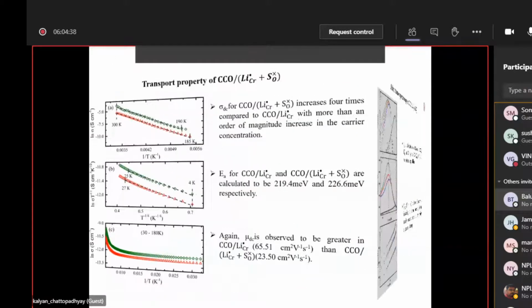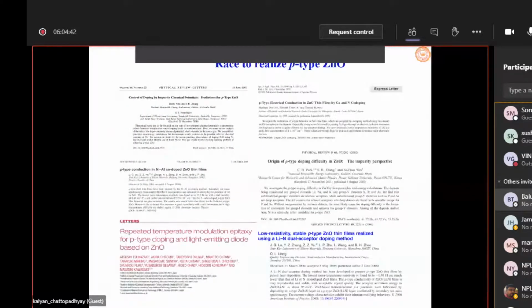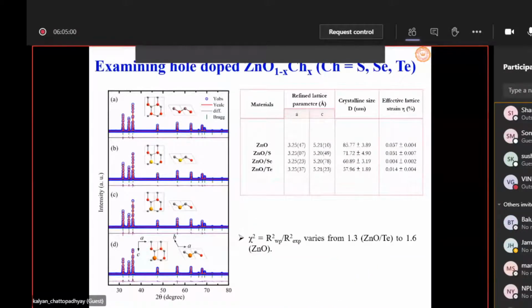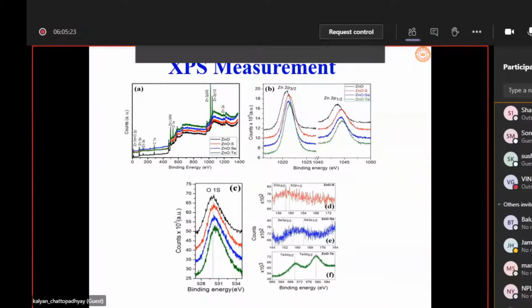I will just take 1 or 2 minutes more to touch upon another very interesting system, that is the P-type zinc oxide. There are lots of papers and work going on about how to achieve this P-type zinc oxide and whether they are stable or not, etc. I will not touch that part, but I will just show that if you incorporate some anionic site doping in zinc oxide, like chalcogens, sulfur, selenium, tellurium at the oxygen site of zinc oxide, then, okay, the detailed material preparation, the doping percentage calculation by detailed Rietveld analysis and phase formation I am skipping. The detailed X-ray photoelectron spectroscopy again confirms the anionic site doping achievement and composition calculation.